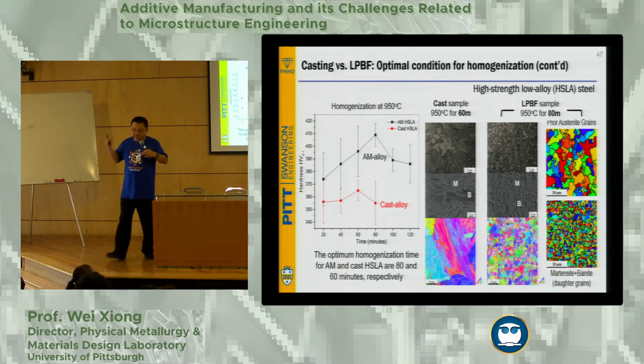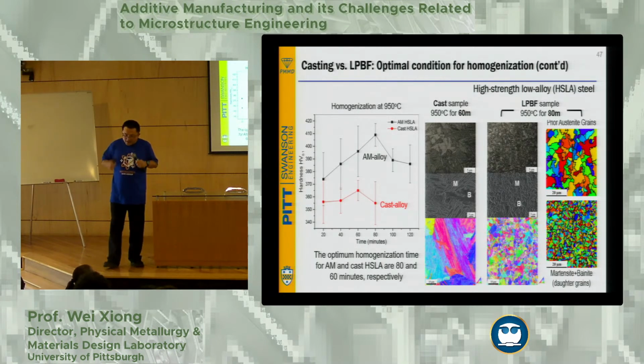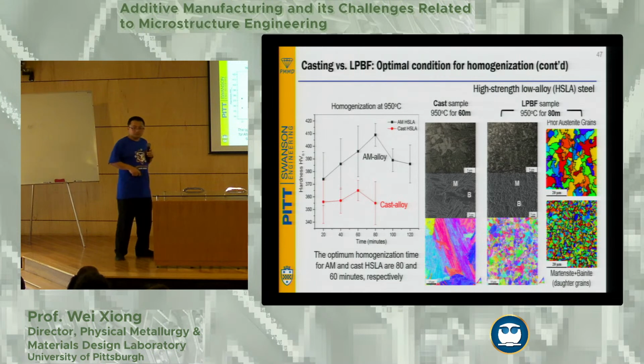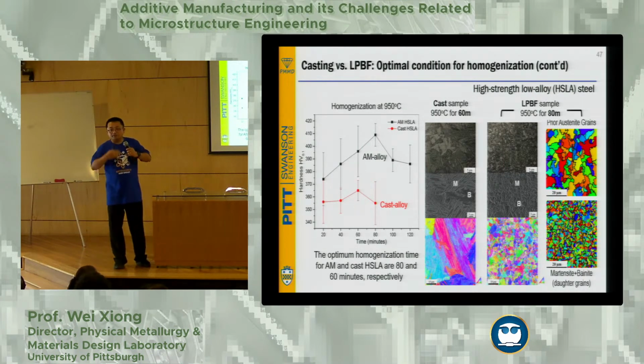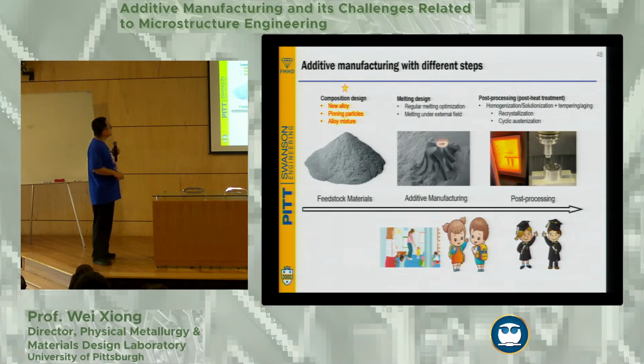Of course, because this is a high energy density additive manufacturing process, laser powder bed fusion, we actually got good luck. We have some good structure with prior austenite, and you can actually get a better matrix structure. However, consequently, if you do the design of the tempering to introduce some other particle strengthening with copper and so on, and also M2C carbide, then you have to change the parameters as well.